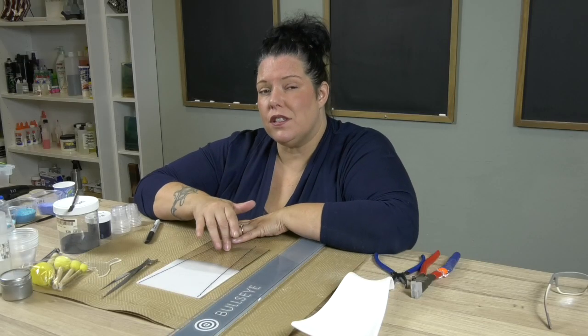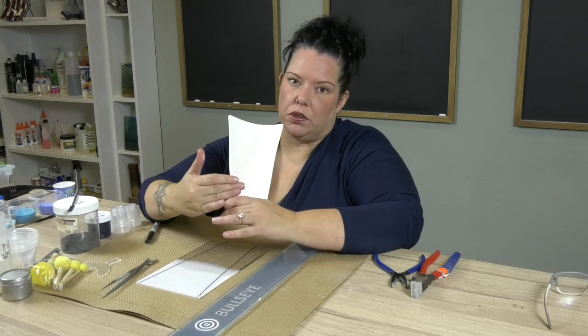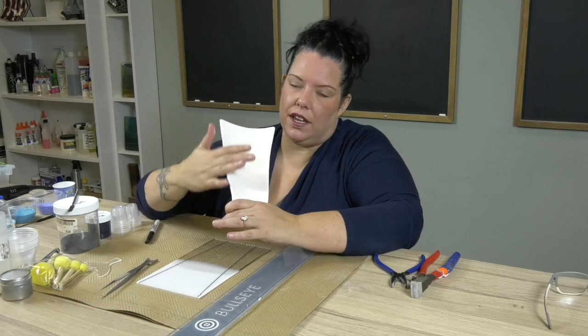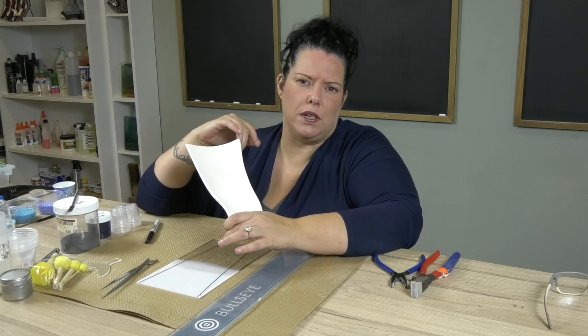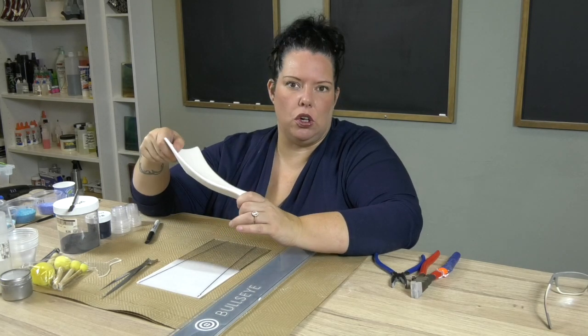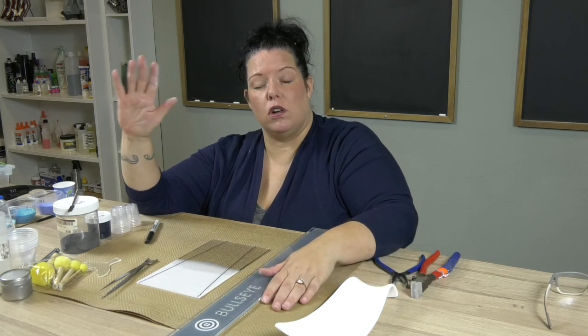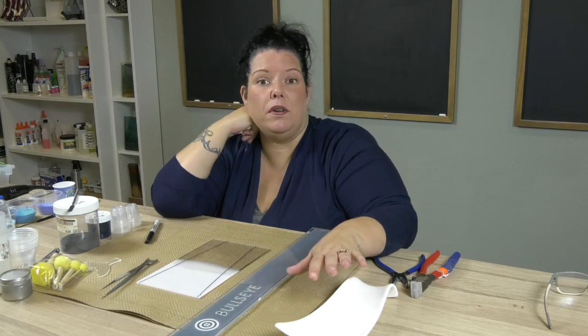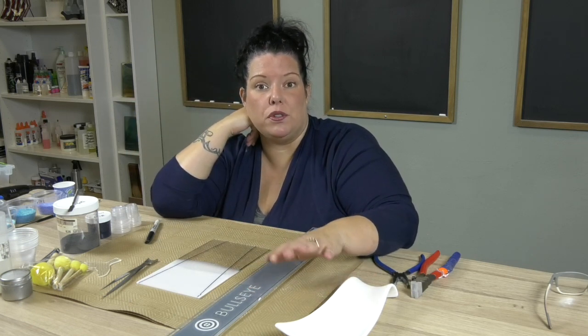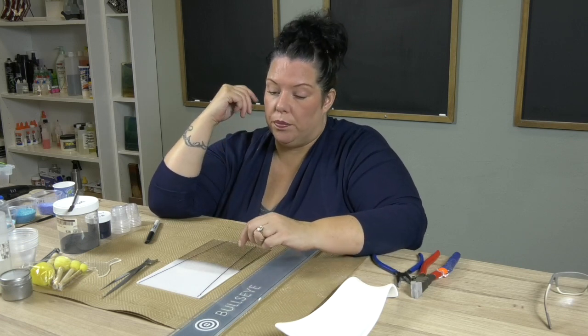So this cut can be a little tricky for the ladle mold. First of all, kiln wash your ladle mold. Everybody knows that, right? Use thin kiln wash. 5-to-1 Bullseye kiln wash, I think, is the absolute best. Give yourself 6-7 coats. Now, I will tell you guys, this was a bear to work out as far as cutting the correct glass shape and firing it in the mold. I did have to slump it 4 times to figure out that schedule for you. So I figured that out. It's going to be in your PDF handout, but it was a doozy.